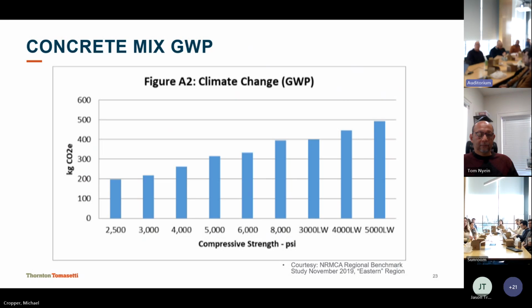What's interesting is that lightweight concrete on the right actually has a higher carbon footprint than normal weight concrete, because the aggregate goes in the kiln and has to be dried out. And then there's usually a higher cement content to get the same strength versus normal weight.